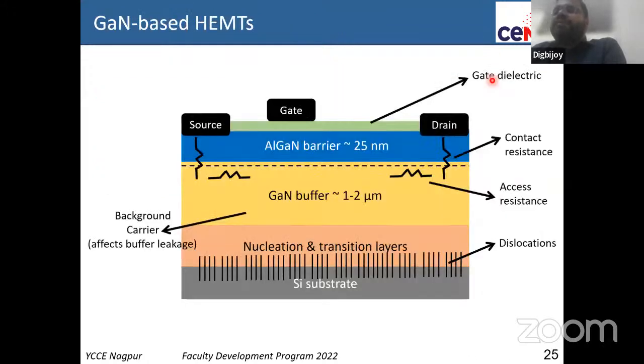Now this is the basic structure of a gallium nitride transistor. I told you there's an aluminum gallium nitride layer on top of gallium nitride, where you have a very high density of 2D electron gas that you use for a high electron mobility transistor, that is used for all these power switching applications. Now, this gallium nitride layer has to be grown on, for instance, silicon. And I told you there are missing lines of atoms that give rise to all kinds of leakage paths. The background in gallium nitride also has a lot of impurities, because of the nature of the growth, that lead to some kind of leakage path.